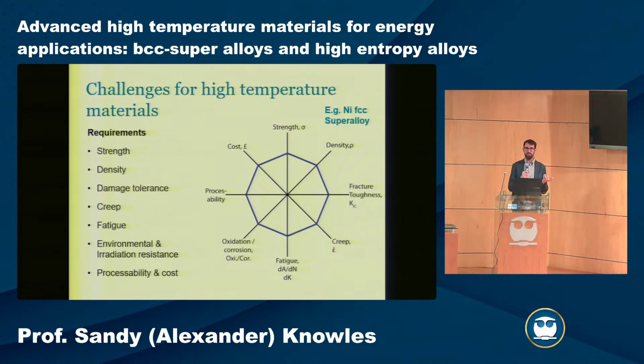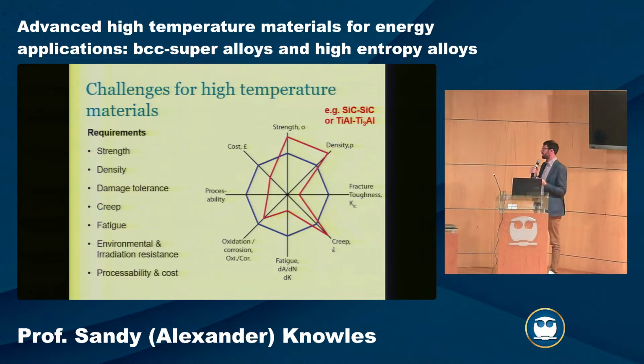So when we want to improve a material, we often try to improve the strength of the material. That's kind of a first proxy for a better material. But we can't do that in isolation. We need to also think, okay, well, it's higher strength, but does it have sufficient ductility? Is it enough density? Does it have the environmental resistance? Is it oxidation corrosion? So when we design a new material, we can benchmark against some previous materials, so nickel-based superalloys. When we look at, say, something like an intermetallic-based material or a composite material of ceramics, so silicon carbide or these titanium aluminide intermetallics, we often gain on strength, but then we lose out on ductility or fracture toughness. And so trying to take a material that creates a better balance of properties is a real challenge.